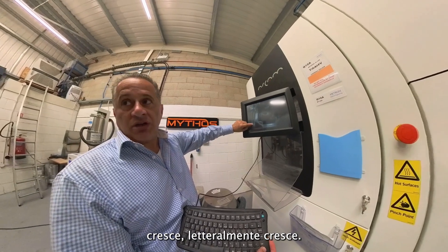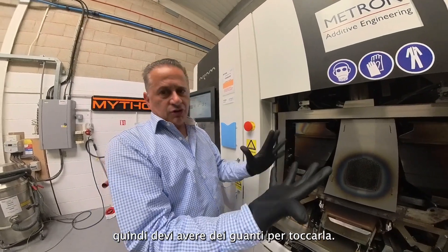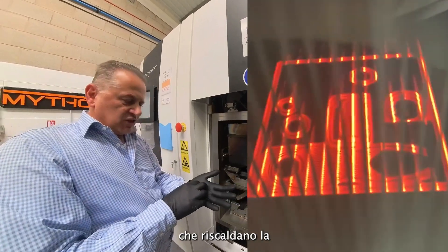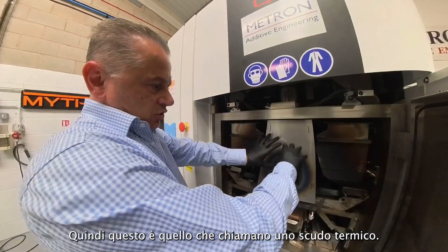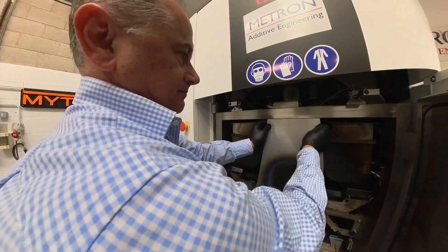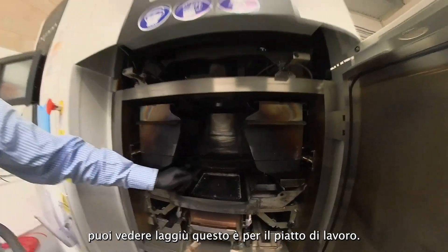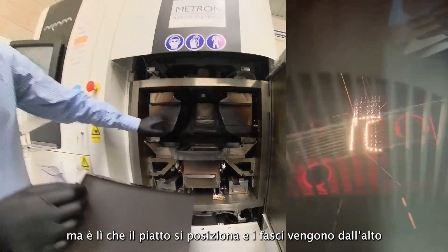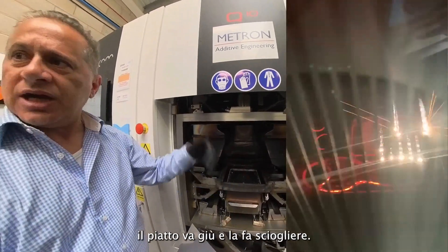The component literally just grows up — the inside of the machine has to be very, very clean, so you have to use gloves. This is an electron beam melting machine, so you effectively have a beam of electrons that heats the titanium powder and melts it, working at a high temperature — around 700 degrees inside. This is what they call a heat shield — it stops the heat coming out. Down there is where the plate sits; the beam comes from the top, the powder sits on the two sides, and the machine puts a little bit of powder down, the table goes down, and the beam melts it, then you do it again.